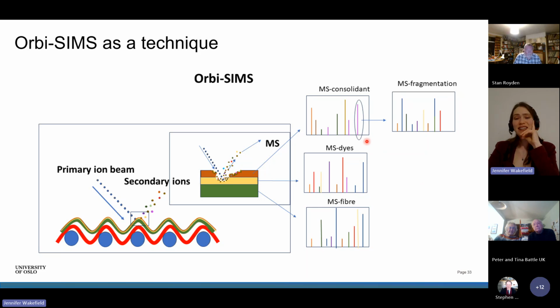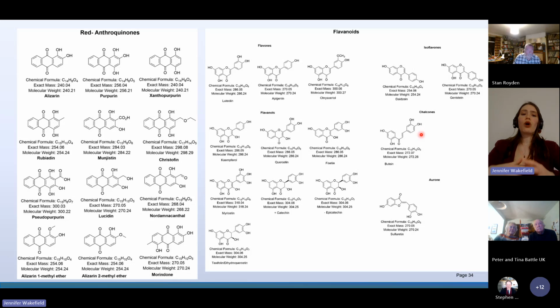Unfortunately, in practice, the dyes prove to have too low a signal to be able to look at this fragmentation pattern, but we still can identify the mass of the compounds. Unfortunately, there are a number of compounds that can have the same mass. So what we do is we search for dyes, and we look at whether they're present or absent. And if they're present, then there's a high possibility that dye was used, particularly if we don't see it in the untreated dye and not in every single archaeological material, to confirm it's not a breakdown product of something else.